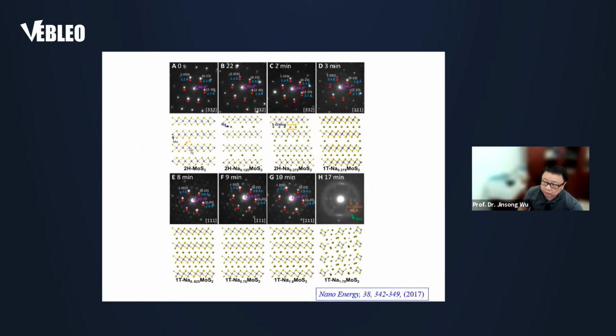from the pristine MoS2 structure, if we have about 0.125 sodium intercalated, the sodium ions are intercalated every 2 layers to form an intercalated structure. But once more sodium is intercalated into the structure, it will trigger movement of the Mo. So now there is a phase transformation from the 2H to the 1T phase. This is when we start to observe a lot of extra diffraction spots, or superlattice spots, inside the SAED pattern. And once more and more sodium is integrated into the structure, the conversion reaction will be triggered. The final reaction product is fine Mo metal nanoparticles, and also sodium sulfide.